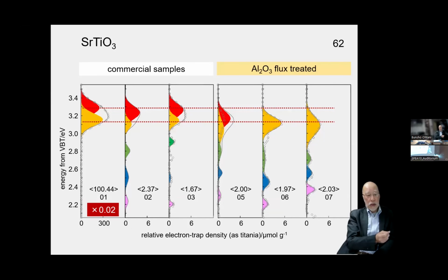And for the strontium titanate case, this is not published yet, but commercial samples contain so many peaks. We have not assigned those peaks, but the surface of strontium titanate is not so simple. And if that is flux treated, Professor Domen introduced this method to obtain highly active photocatalysts, but this induces so much difference for the samples and gives different peaks. So the surface structure is completely different, and the SrTiO3 surface is not only those surfaces; other kinds of surfaces are exposed.